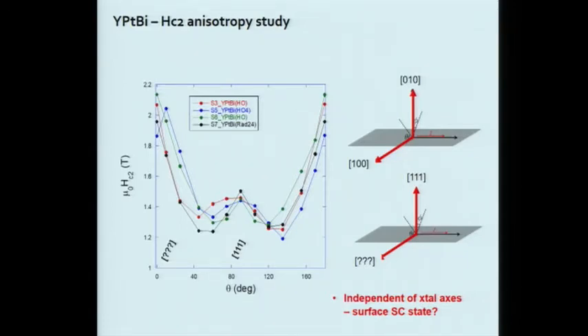HC3 is just an enhancement of the superconducting state on a surface. So you can have an enhanced HC2. We don't understand these states. We're exploring them now. We're doing further experiments. But basically, I wouldn't say demagnetization factor, but it could actually be some surface state that's somehow enhancing the HC2. And we don't quite see it when we're perpendicular.